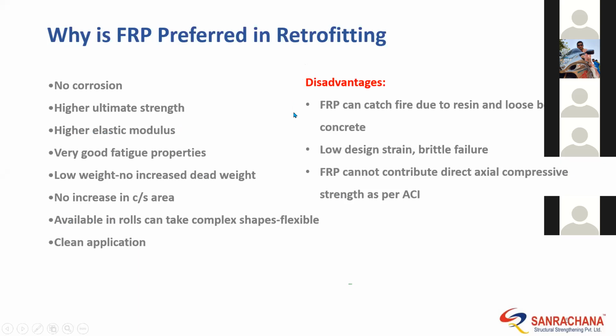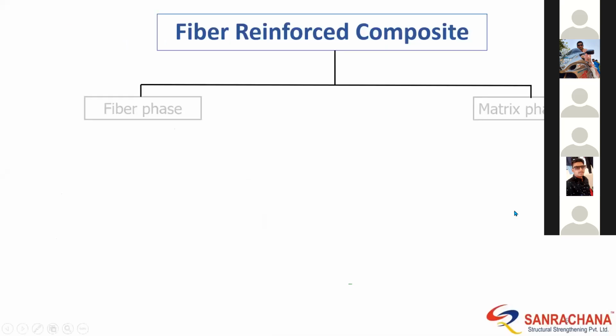And the disadvantages of using FRP, a few of them you need to really know, that it cannot be directly used as a compressive strengthening method, like axial compression. ACI does not recommend using FRP. FRP is a very good material for flexure as well as for shear. But for axial compression, unless it is a circular column wherein the mechanism is different, through hoop strengthening, if the cross section of the column is not circular, then typically we don't use FRP for axial compressive strengthening. We will look into this in detail in further slides.